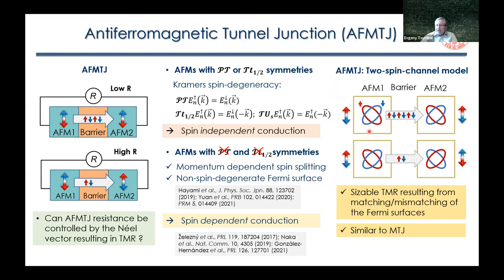So imagine that we have two antiferromagnetic electrodes that are the same, so they have the same kind of Fermi surfaces, shown schematically here by these two ellipses, but there is no overlap between these two Fermi surfaces. So they're different for up and down spin electrons. So in this case, if you have parallel aligned Néel vectors, we have perfect matching between Fermi surfaces, and up and down spin electrons would tunnel efficiently to the available states in the right electrode.